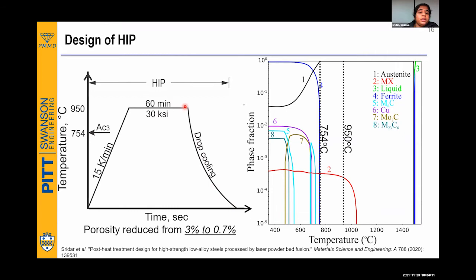Now, this cooling rate is the worst part of HIP, I would say. Why? Because this cooling rate cannot be as fast as water quenching, which is what we generally do for heat treatment. Drop cooling means that you just switch off the furnace after your HIP process. That is, you heat it, take it to 950 degrees C, hold it for 60 minutes at 30 KSI, and then simply switch off the furnace. This is the profile which the company gave to us, so we simulated this profile. And another cooling profile was also given to us by the company.